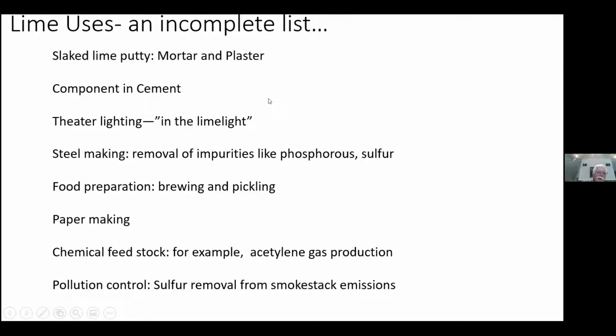An interesting aspect of lime is that it also has this property called thermoluminescence. And when you heat it up, it emits a very bright whitish light. And in the 1800s, lime was actually used together with gas jets. The gas jets would heat the cylinders of lime up. The lime would start to thermoluminesce and produce this brilliant white light. And that was the limelight that was used in theater lighting. And so our phrase of being in the limelight basically goes back to that use of lime, being in effect the spotlight produced by this heated lime.